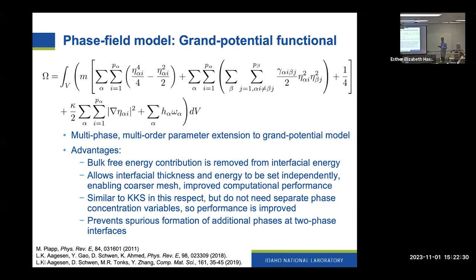And so a couple of nice advantages of this model are that it removes the bulk free energy contribution from the interfacial energy. And so that allows us to set the interfacial thickness and interfacial energy independently. And that allows us to use a coarser mesh, and so that gives us improved computational performance. So removing the bulk energy contribution from the interfacial energy is similar to the Kim-Kim-Suzuki, or KKS, phase field model, which some phase field folks are probably familiar with.